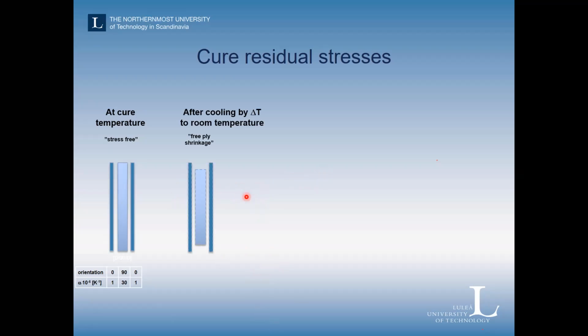If we just consider the free plies, the outer plies, which are in the 0 degree direction, they don't want to shrink at all because it's carbon fibers with very low thermal expansion coefficient, whereas the middle layer wants to shrink. But because they are glued together, they will shrink just the same amount. This means that the 90 degree layers will be subjected to a tensile stress because it wants to shrink, but it can't shrink, whereas the 0 degree layers are in compressive loading.